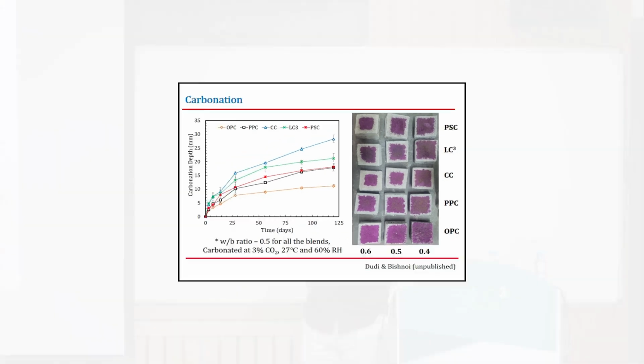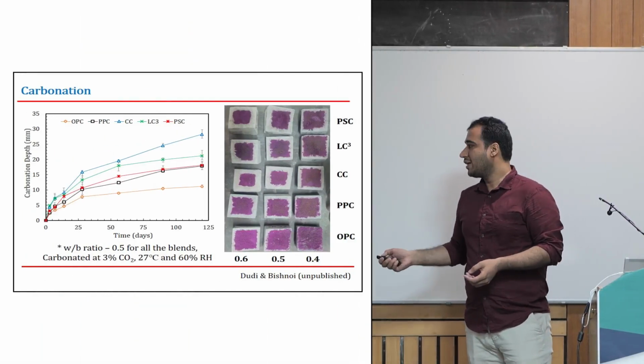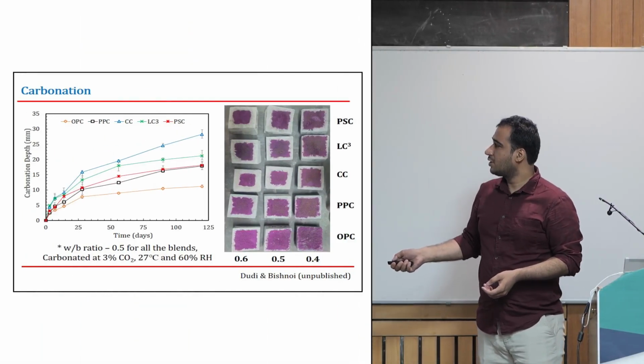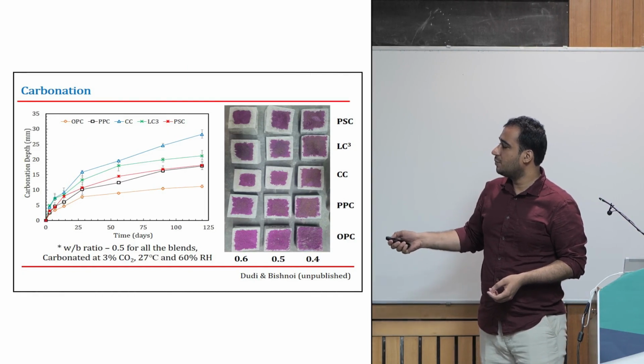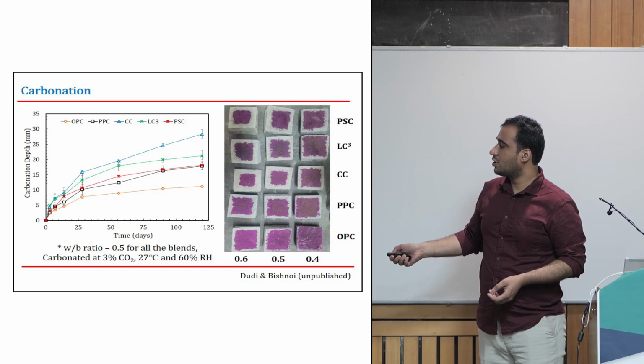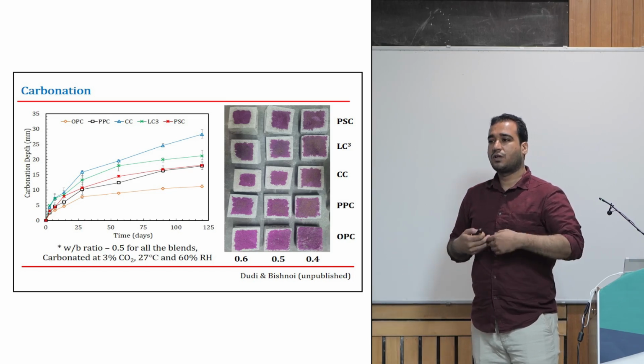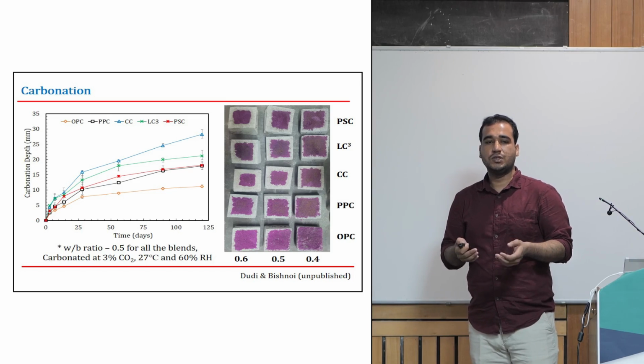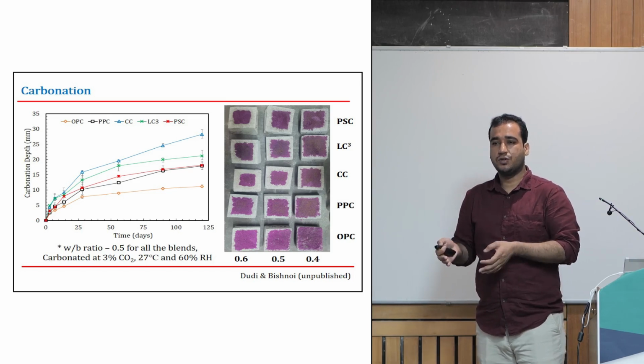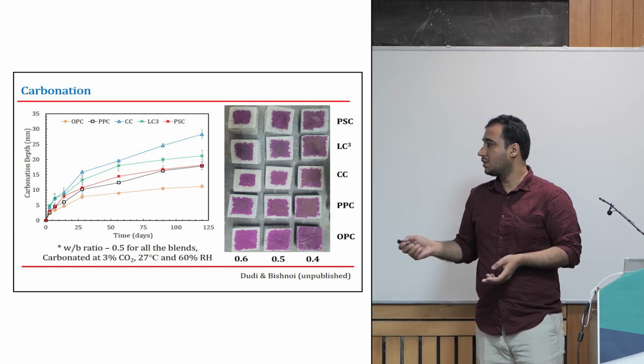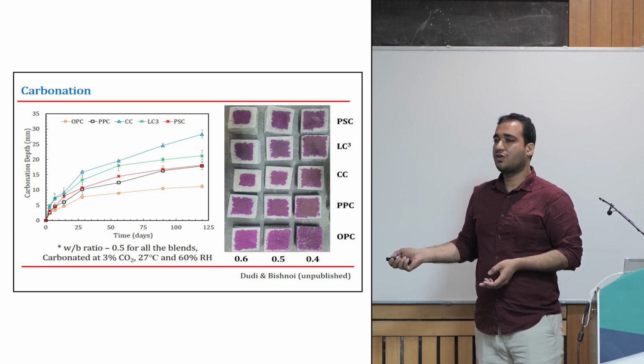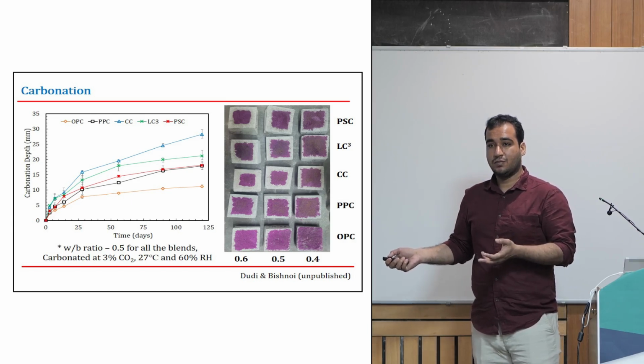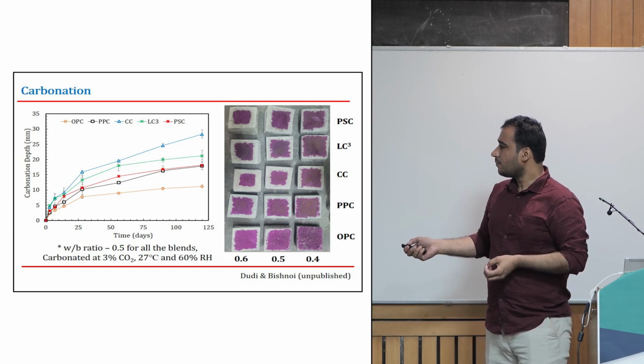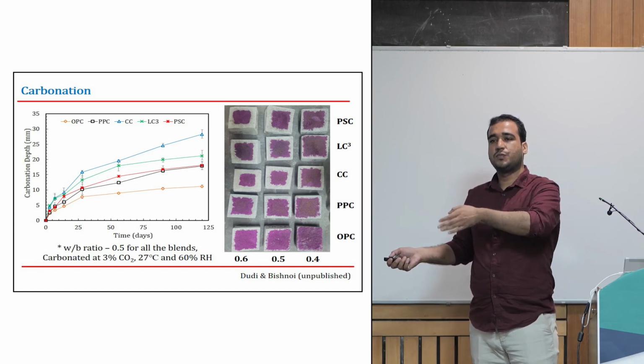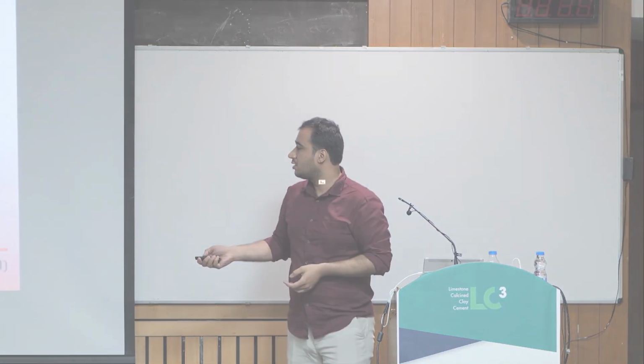But consequently, depending on the water to cement ratio, a common approach that we use for tackling this carbonation is to reduce the water to cement ratio. You can see at 0.5, the carbonation depth is much higher, and at 0.4, it's much lower than at 0.5. So if carbonation is your major cause, what you can do is simply change the water to cement ratio if you are worried about the carbonation. Changing the water cement ratio will provide you enough time before the structure's passive film gets destroyed.